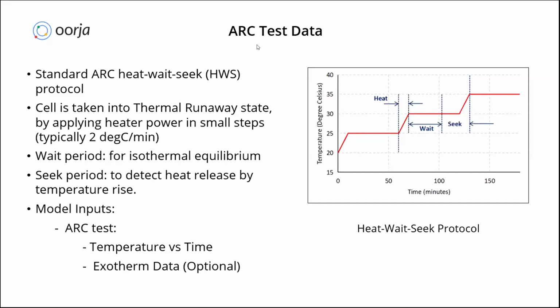And for that, the instrument will be recording the temperature versus time data along with many other parameters. What we need in Urja is mainly the temperature versus time data along with the exotherm data. Exotherm data is nothing but the data collected from the TR trigger point to the maximum temperature reached by the cell. With these two data sets, we can extract the useful information which is required to build the cell and the pack level thermal runaway.